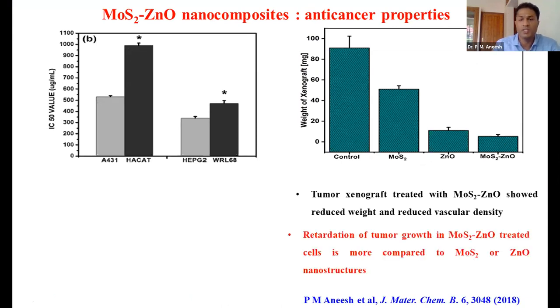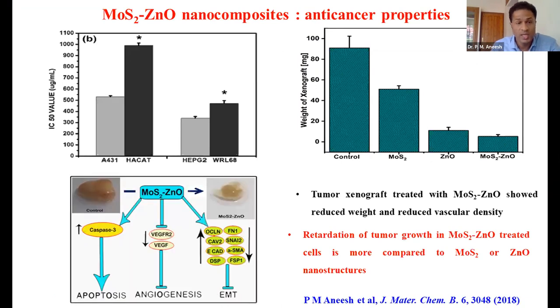The same thing we checked with the MoS2-ZnO as well. We found that when it is treated with this MoS2-ZnO, it activates the caspase 3 enzyme, which results in the apoptosis process, and at the same time it down-regulates the genes corresponding to angiogenesis, the pro-angiogenic genes.